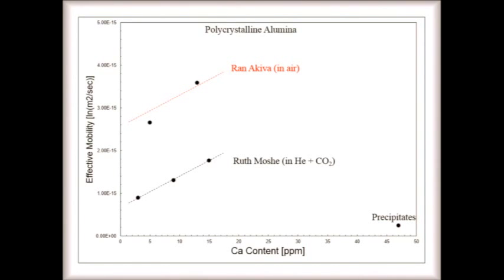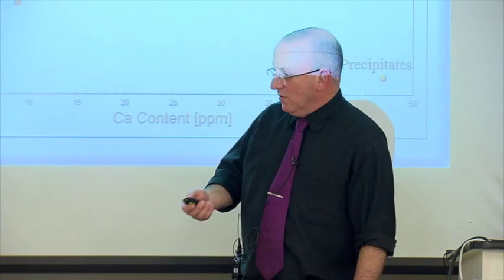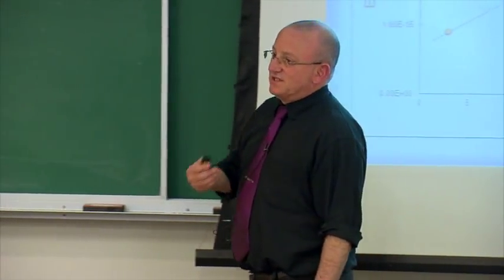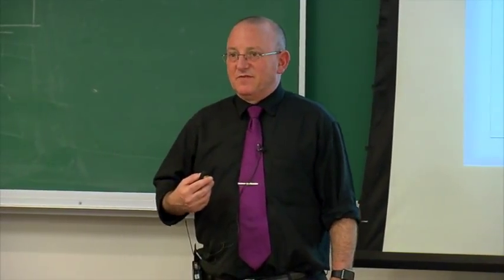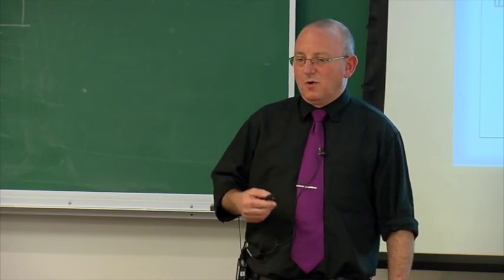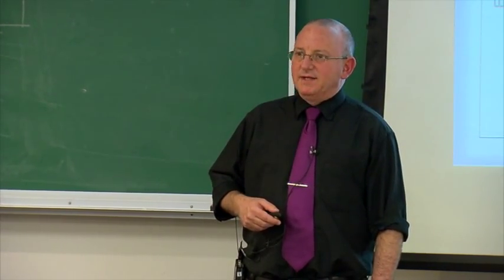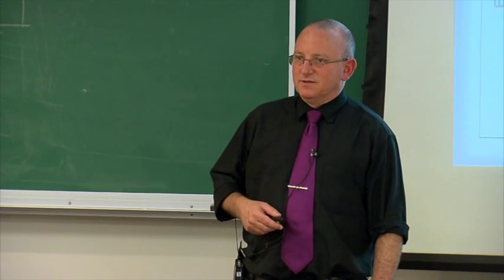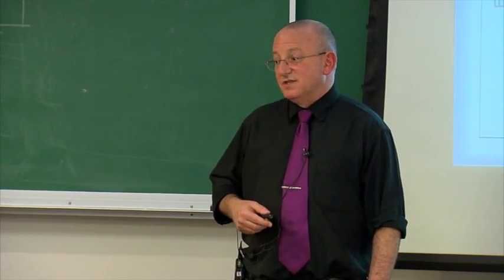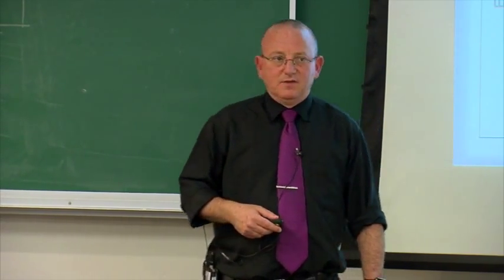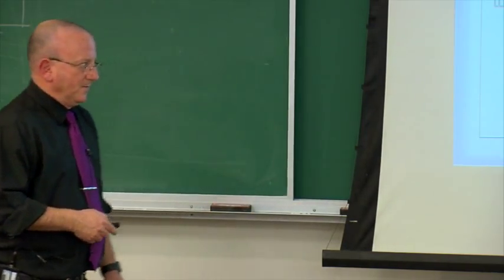It's just that we rarely see it because we sinter in air most of the time, and there's very little of it. But if you start to sinter in a protective atmosphere where you can introduce carbon in one form or another, it plays all kinds of interesting roles at the grain boundaries, including reports that it causes strengthening of grain boundaries. And these are some fracture experiments done in Oxford.